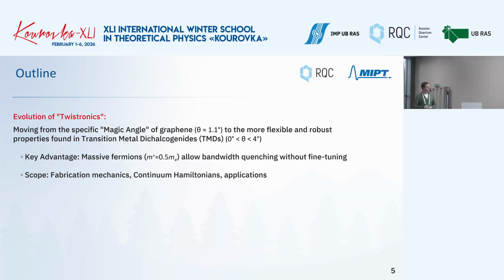So the outline of the talk is what I call the evolution of twistronics. There is a field called twistronics, where you have, for example, two monolayers of two-dimensional materials, and then you put them on top of each other with some specific twist, and this twist allows you to obtain different properties. And throughout the talk I will show you these things. So we will move from the specific so-called magic angle of graphene, which is around 1.1 degrees, to the more flexible and robust properties found in another type of 2D materials, transition metal dichalcogenides, where this so-called magic angle can be broader. So not only 1.1 degrees, but from 0 to 4 degrees.